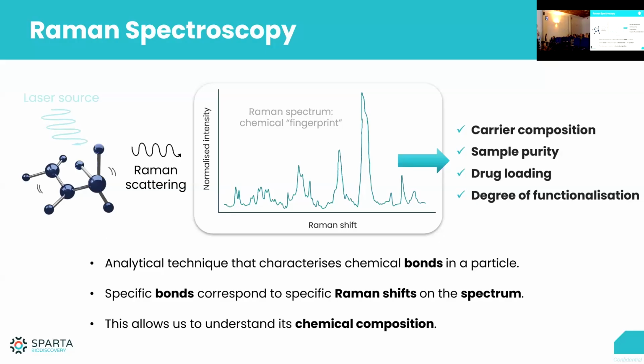Now, what's actually happening? We shoot this laser at these nanoparticles, and all these photons hit the nanoparticles, and the vast majority of the light scatters elastically with the particle, which means that the photon with one wavelength that comes in from the laser leaves the particle with the exact same wavelength. This is interesting. You can do some scattering analysis for the size of the particles, for instance, but you can't see any chemical information there. Now, a very small fraction of that light also scatters inelastically with the molecular bonds. And this is really the Raman effect that we're looking at.